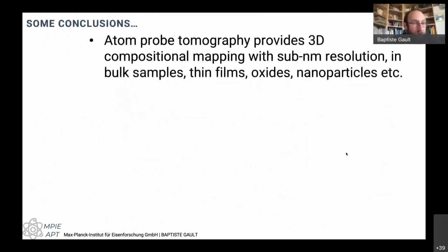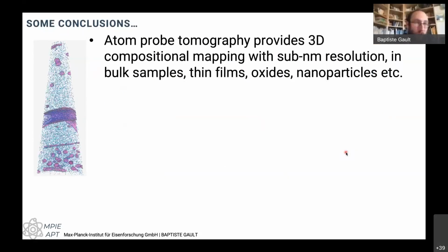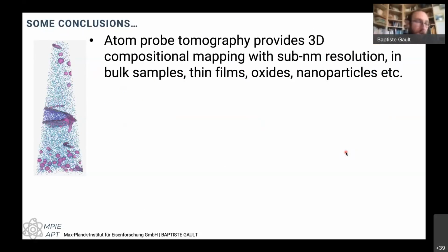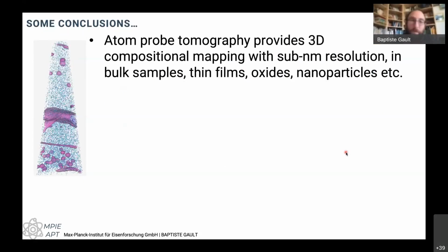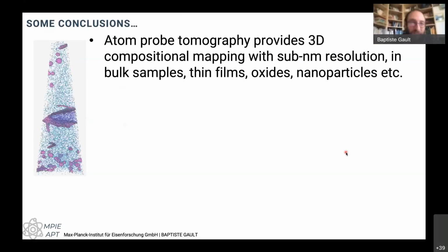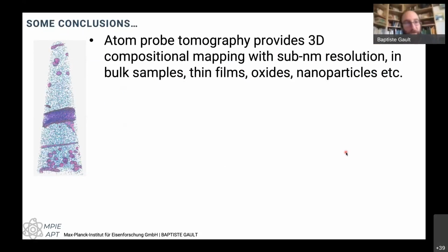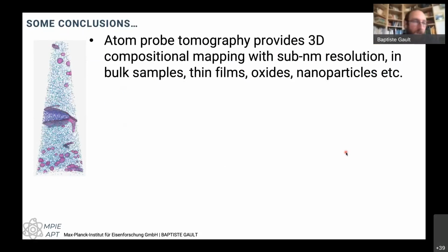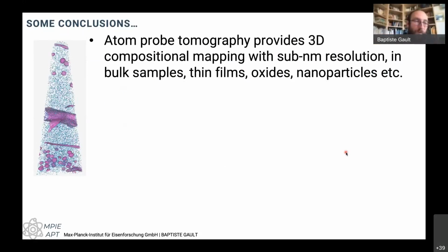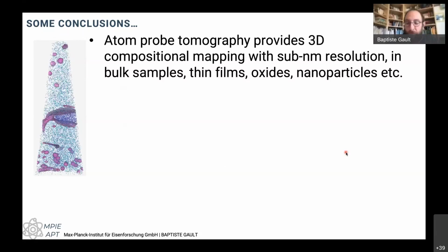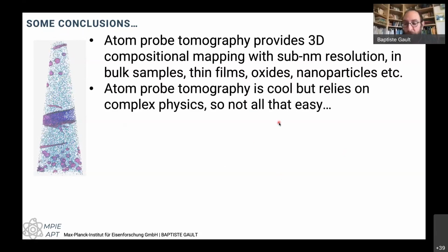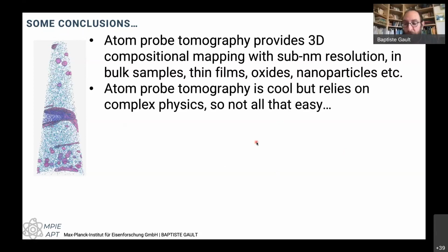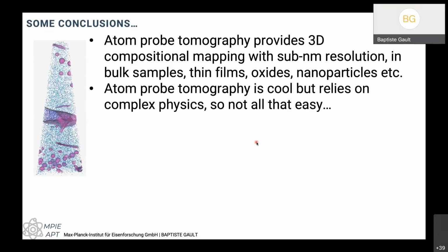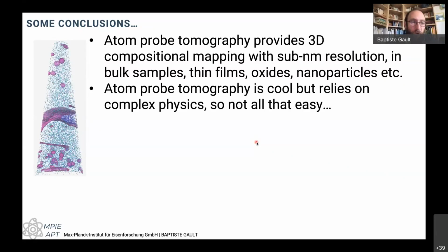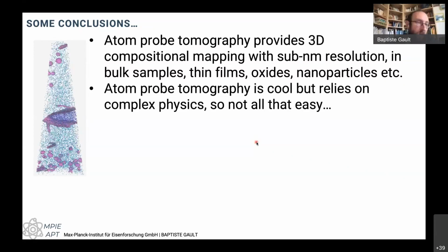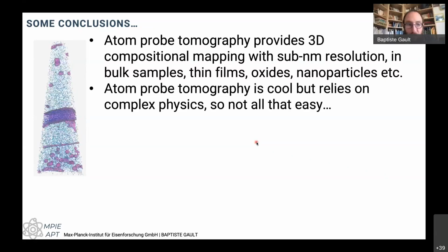Anyway, just to conclude, what atom probe does well is to provide a three-dimensional compositional mapping of solid materials, mostly bulk, but also thin films. We can look at oxides, nanoparticles also, but it requires some tricks. But that gives you an idea of how the species are distributed within your sample. And it's cool, but there's some pretty complex physics behind it. So sometimes the interpretation is not as straightforward as we would like it to be. It doesn't mean that we shouldn't do it. It means that we have to be a bit more careful sometimes with the interpretation. But again, that's like any measurement that we make.